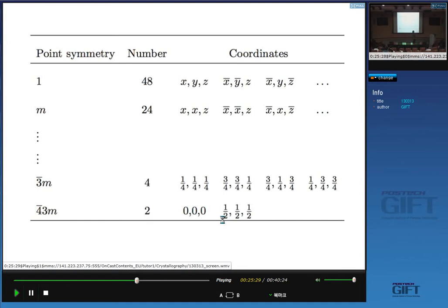So the problem is that when you do diffraction experiments and so on, there is a certain part of information which is lost, which doesn't allow you to find where the atoms are. So you can work out the symmetry of the cell, the lattice parameters, and so on. But then you have to go through a trial and error process: if I place my atoms here, what is the X-ray intensity I will get? So that's why you need to do some guesswork: if this is the space group, and if I locate the atoms here, what is the intensity I will get in my X-ray diffraction experiment? And this is why you get Nobel Prizes for solving structures of DNA and so forth, because there's a lot of guesswork involved. Not completely guesswork, it's what you call educated guesswork.